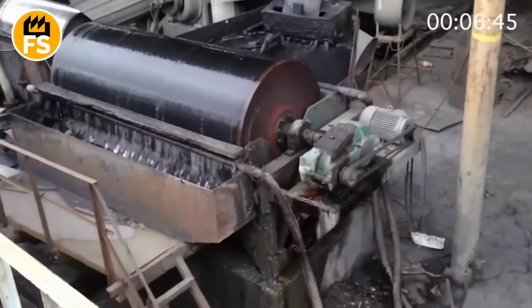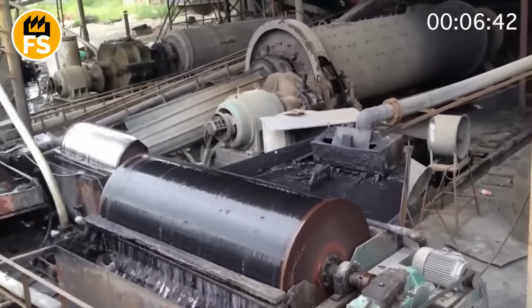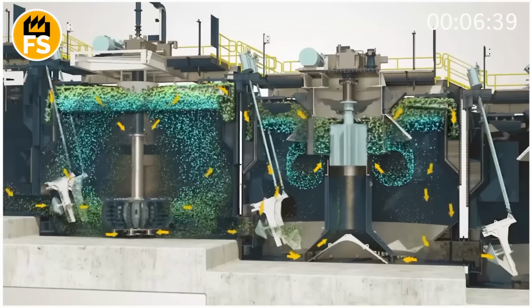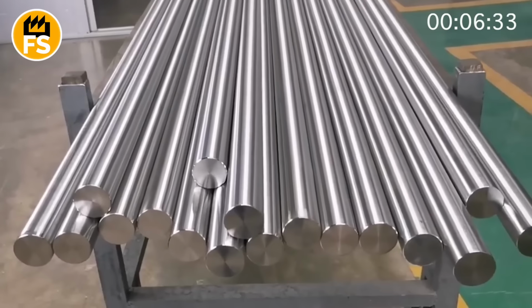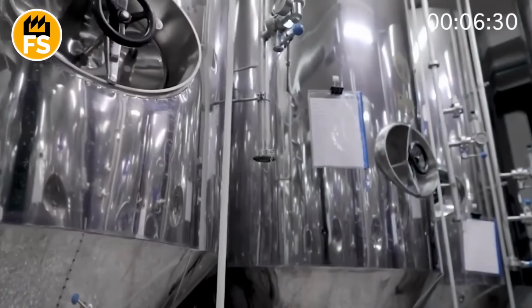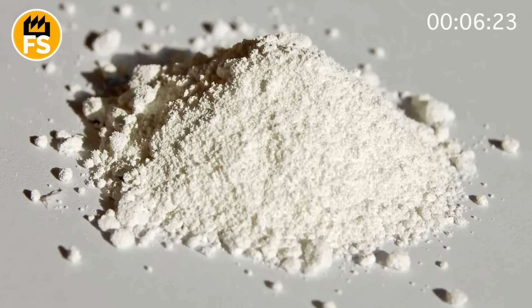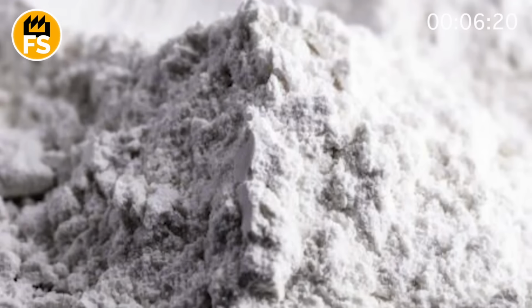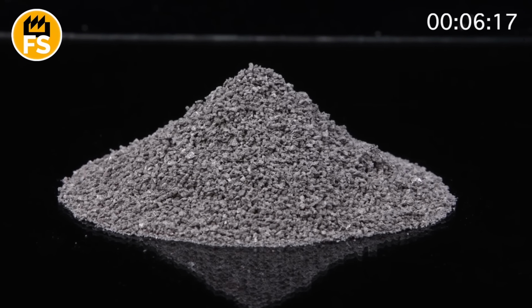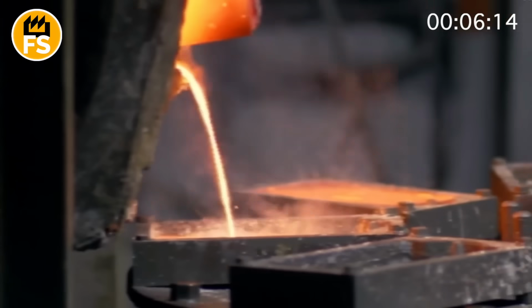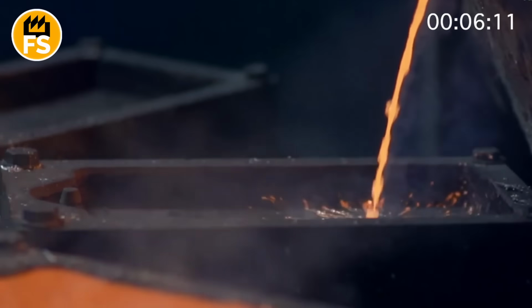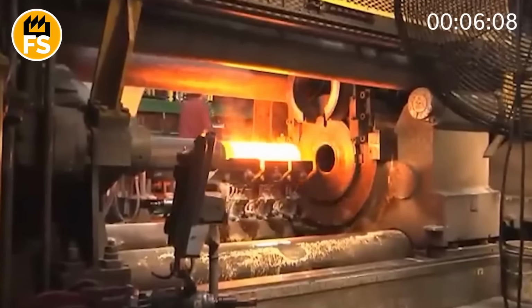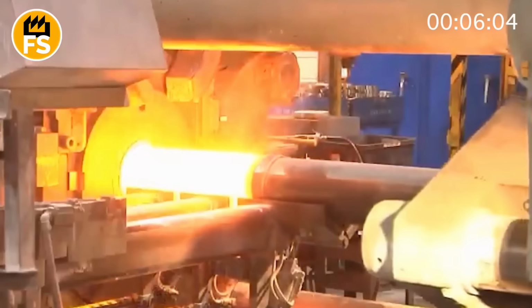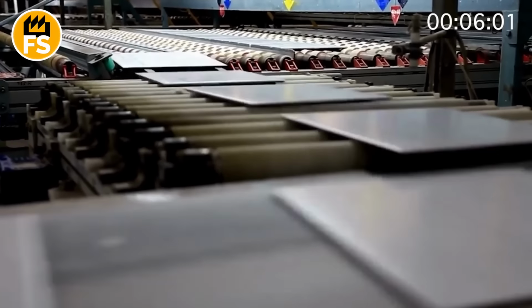Then, the concentrates are subjected to chlorination, which results in the formation of titanium tetrachloride, a volatile substance that is purified by distillation. This process allows for the removal of impurities and the production of a high-purity intermediate product. Next, titanium tetrachloride is reduced with magnesium or sodium in special reactors at a high temperature in an inert atmosphere, producing spongy titanium, a porous metal powder. This spongy titanium is then subjected to pressing, melting, and casting to obtain ingots or blanks for further processing. The production of titanium is energy-intensive and expensive due to the complexity of technological processes and the need to work in high-purity conditions.